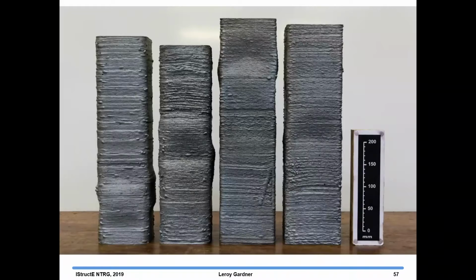So we then carried out a series of tests. These are compression tests for square hollow sections. And generally speaking, their failure mode was similar to what we would normally expect. So this is local buckling with the alternate faces buckling inwards and outwards. This is what you would normally see. But we did see, when we looked at the 3D laser scan models, that failure initiated at the points of higher imperfections or thinner material in those models.